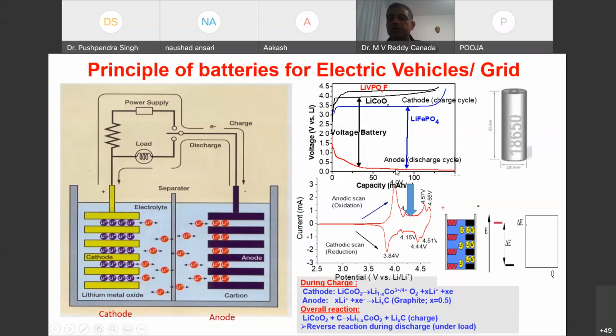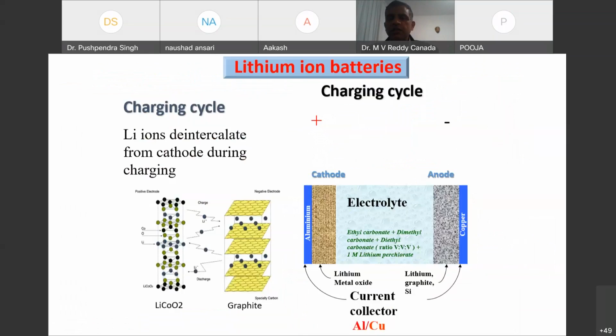So the major challenge is that if you want to get high energy density, we have to see the difference between charge and discharge should be higher, which is good. And also we have to get extended capacity, for example. So presently we have something around 200 maximum we can go. If you go to 400 or 500, automatically we can improve the energy density. Also we can reduce the weight of the batteries.